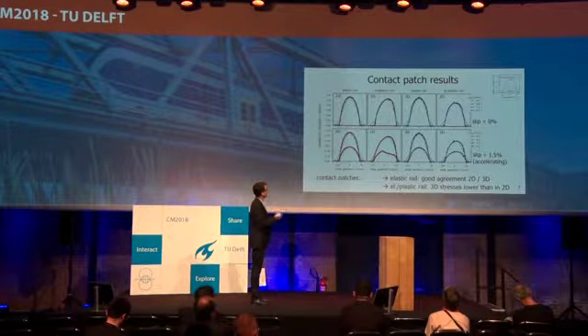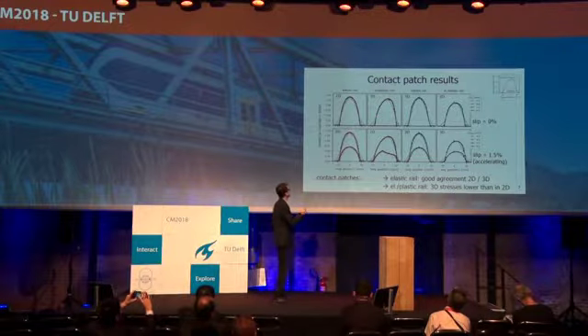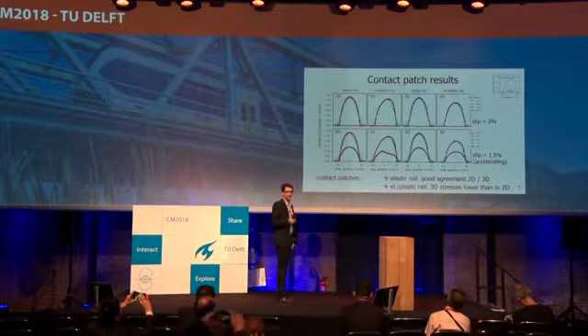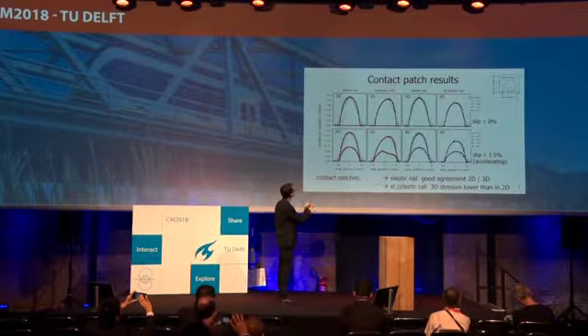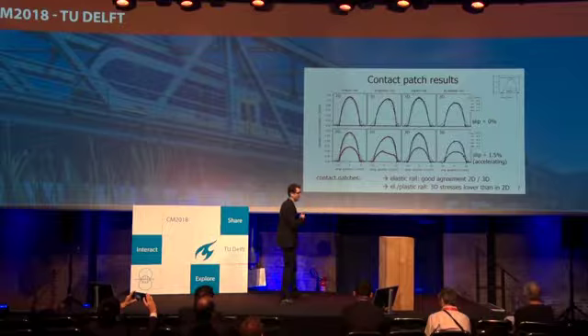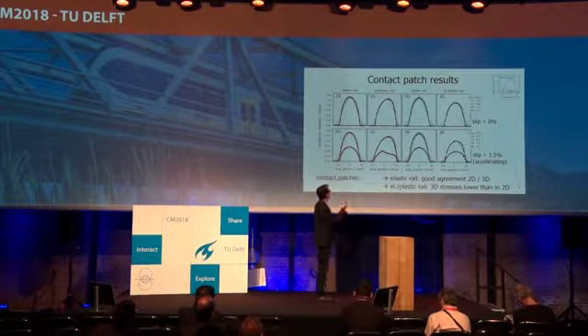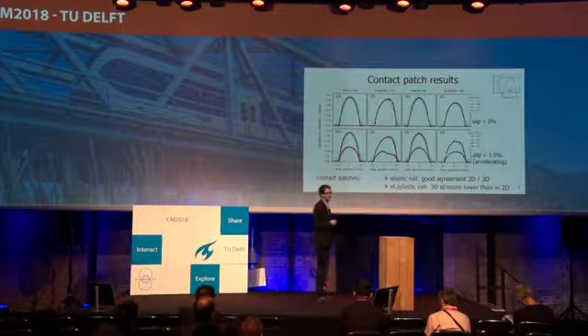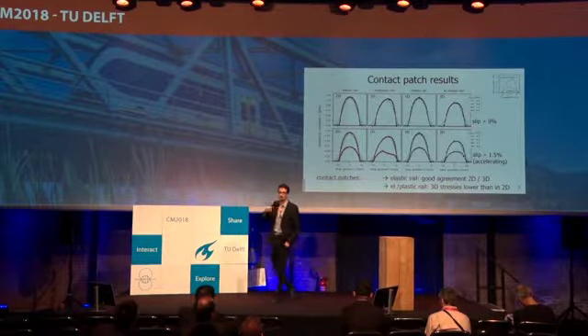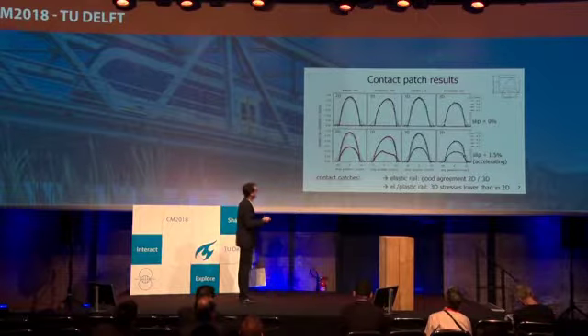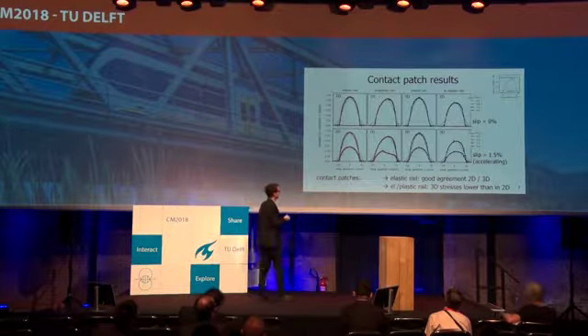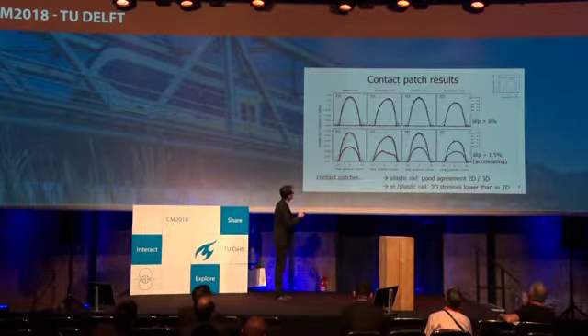Okay, now let's start looking at the contact patches. Here we have the results for a slip of 0%. We set up the 2D model to have the same contact patches in the elastic case with the Hertzian formulas. We see that fits pretty well. If we introduce elastic plastic material properties of the rail, we see that our contact patch is a little bit unsymmetrical for our first time when we roll over the plastic rail. If we introduce slip, we see we also have this shear or traction stresses here, and also the contact patch becomes a little bit asymmetric when we roll over it.